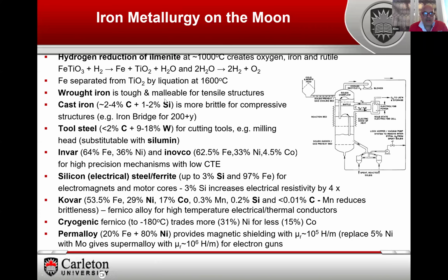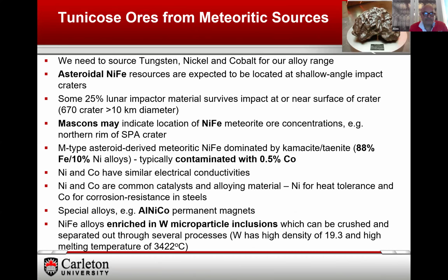So, for example, we'll try to minimize the amount of carbon we use, but essentially we can have cast iron with a bit of silicon, tool steels, though we could substitute for that with silumin, which we'll look at later. We can create Invar, silicon steel, Kovar, cryogenic Fernico, permalloy. So we're starting to build up, with access to a certain limited number of materials, an array of alloys for different applications.